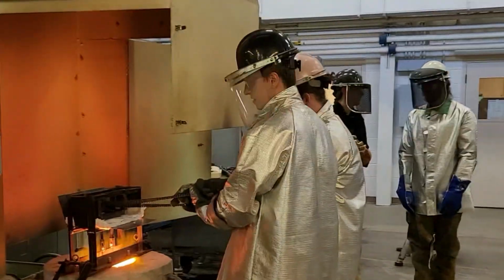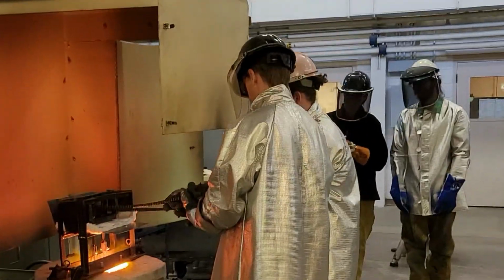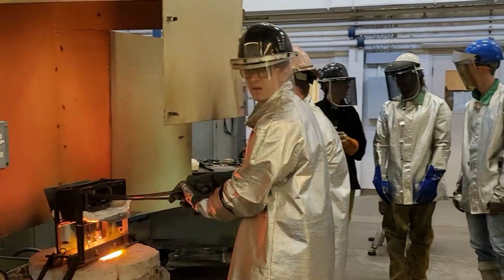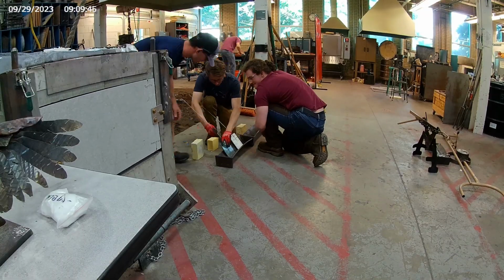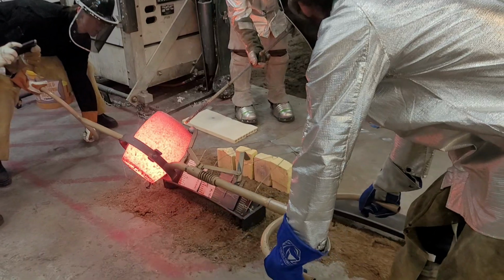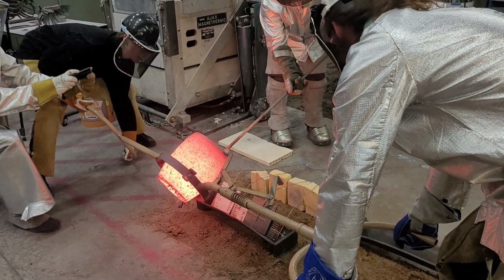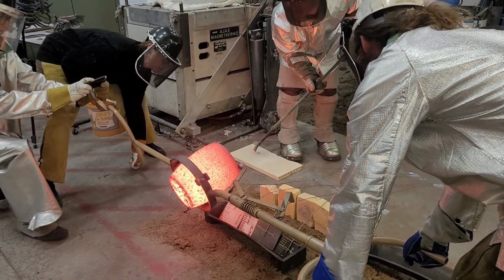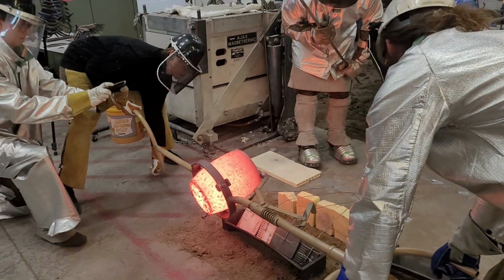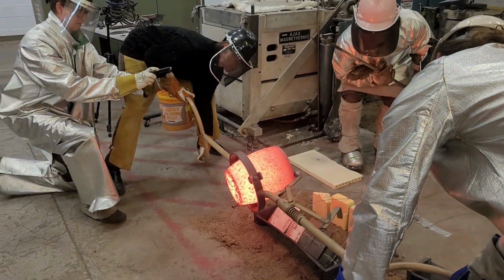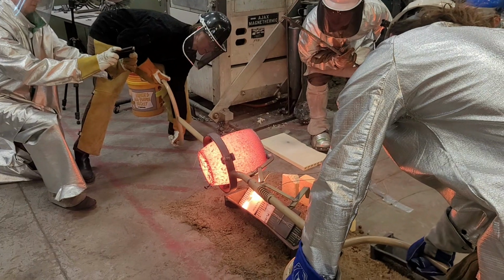Once dwell testing was complete, the regolith melt was poured across 2 sets of matching silicon carbide and molybdenum tiles. Similar to the dynamic test, 1 set of these tiles was coated with boron nitride. The pour test was conducted in order to measure the flow rate of molten material across each refractory media, with thermocouples tracking the heat profile of the refractory tiles, and then the tiles being examined for damage once testing was complete.